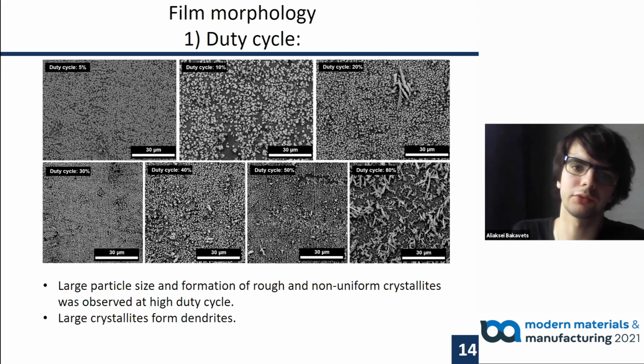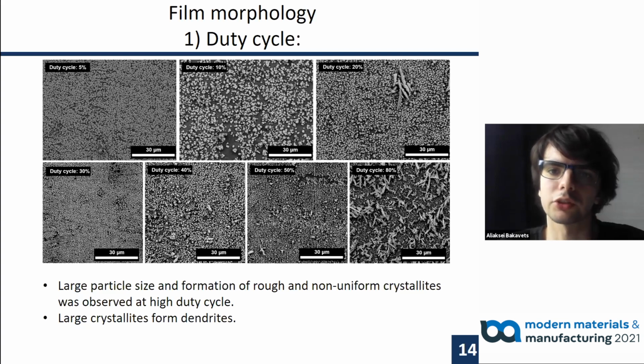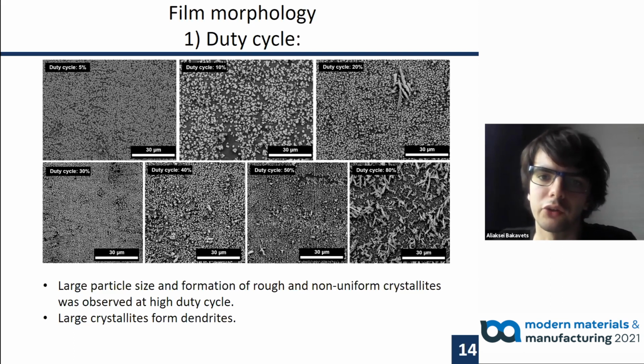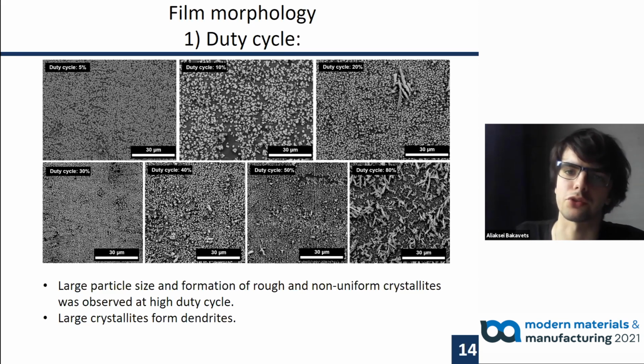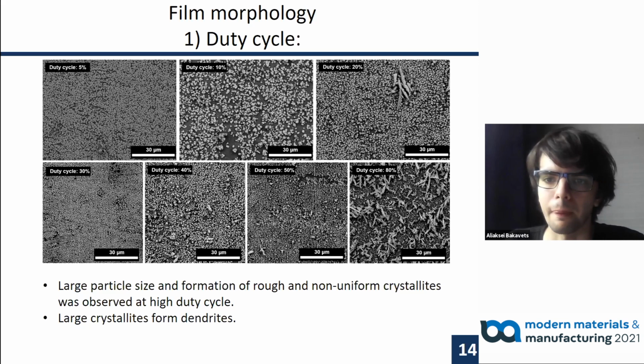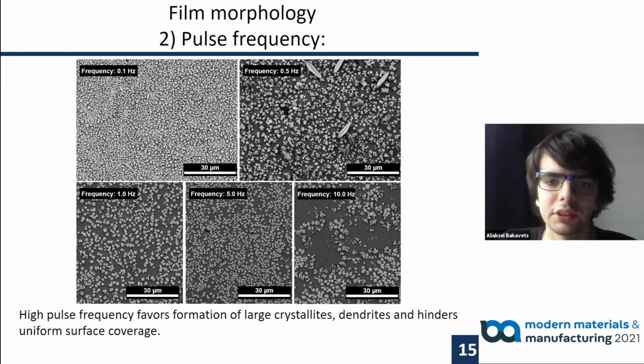The morphology of the electrodeposits was controlled by parameters of the pulsed electrodeposition. First, the duty cycle, which is the ratio of the cathodic and anodic steps duration in the potential control waveform. The particle size generally increases with duty cycle, which results in rough, non-uniform films at too high duty cycle. As for the pulse frequency, excessively high pulse frequency leads to the formation of large crystallites and dendrites, but alternation of the deposition and refinement potential at moderate frequency was required to exclude contamination of the product by metallic bismuth.